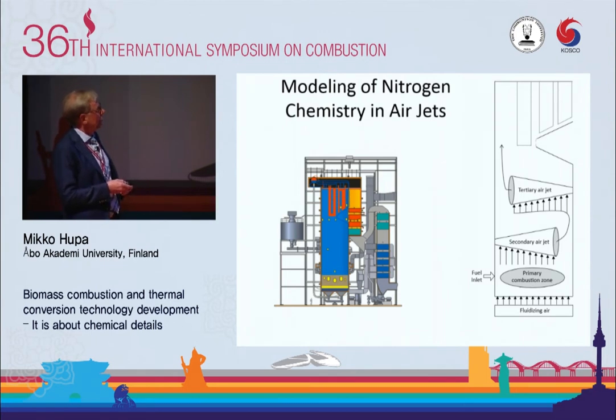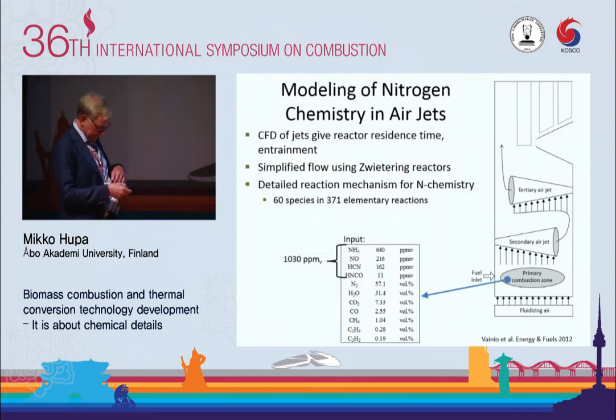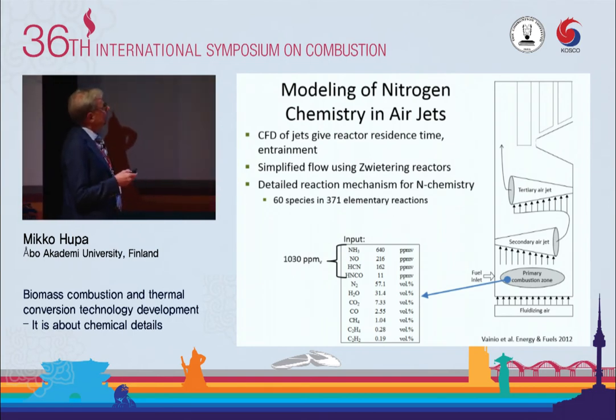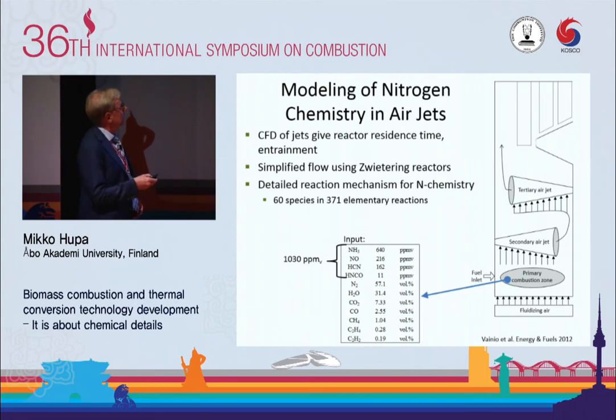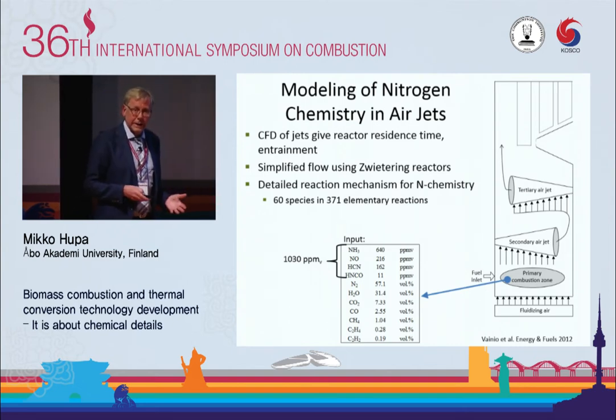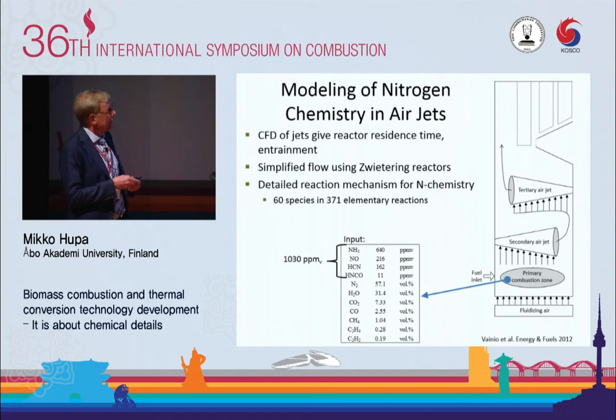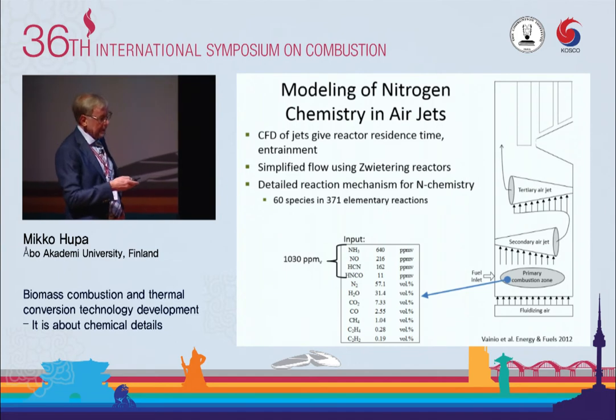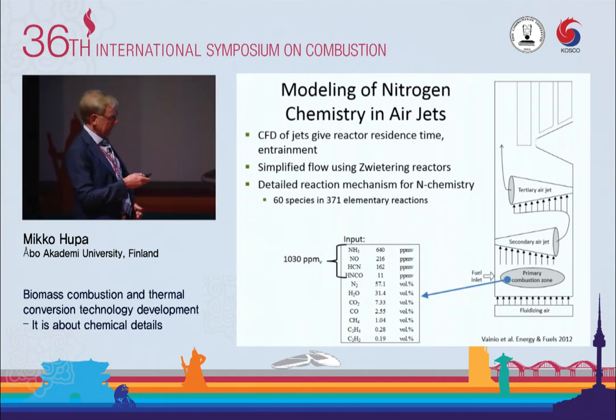And we created a model where we simplified the furnace in the way that we assumed that most of the chemistry takes place in the jets. And this is the approach we used. We first calculated the jet size and entrainment, approximated by computational fluid dynamics. Then for chemistry, we used detailed chemistry. But the reactor assumption here was that we have a gradual, continuous entrainment of flue gas according to the entrainment laws, using this Zwietering reactor, so smooth, continuous feeding. This way we can put the complete chemistry in and see what happens.